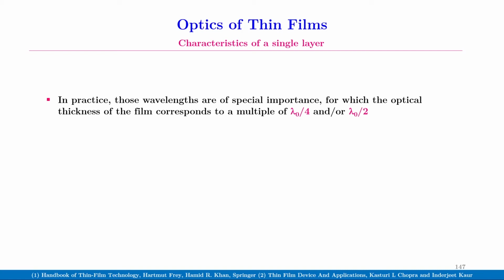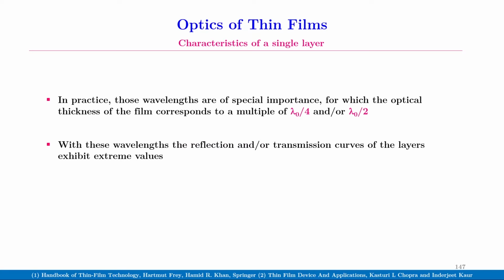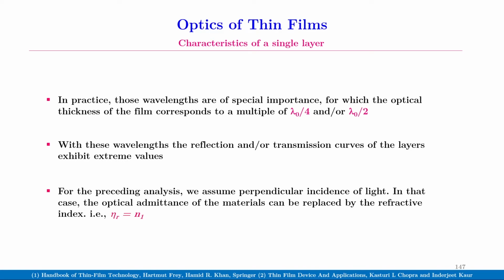In practice, those wavelengths are of special importance for which the optical thickness of the film corresponds to a multiple of λ0 divided by 4 and/or λ0 divided by 2. With these wavelengths, the reflection and/or the transmission curves of the layers exhibit extreme values. For the preceding analysis, we assume perpendicular incidence of light. In that case, the optical admittance of the material can be replaced by the refractive index, that is η_r equal to n1.